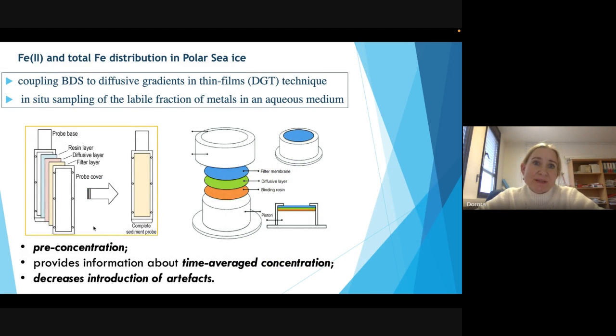Another environmental application of this technique of beam deflection spectrometry is its application for determination of iron species in environmental samples. The sample that was of our interest was polar sea ice. For that purpose, we coupled our technique to the technique called diffusive gradients in thin films. That enables in situ sampling of the labile fraction of metal in different aquatic media or sediments. So the probes look like that. This is the probe that we use for determining iron species in waters such as lakes, seas, rivers, and in sediments.